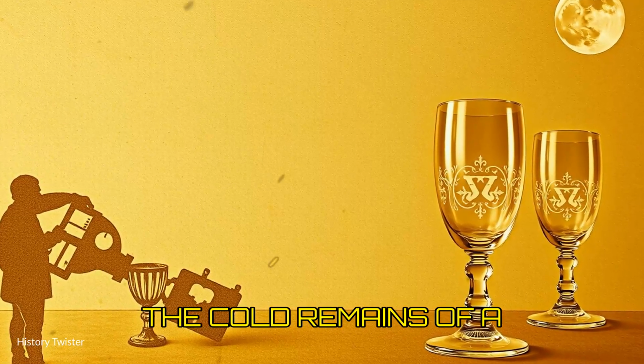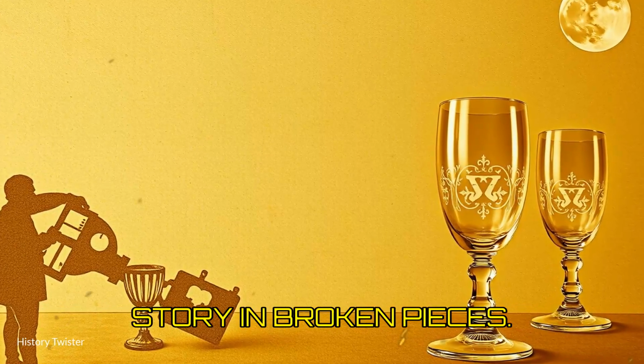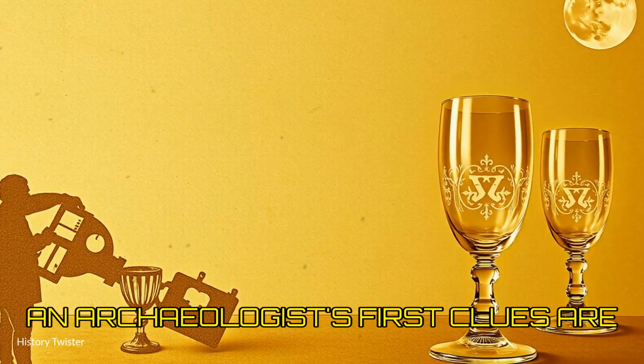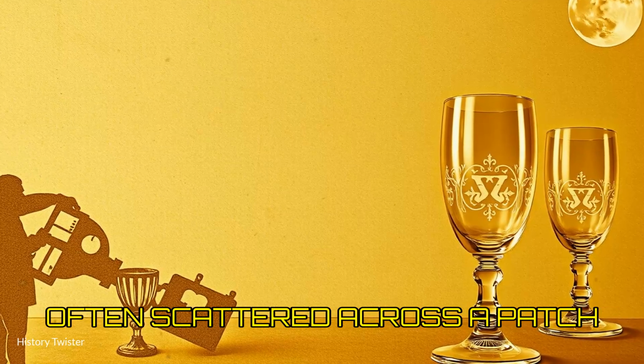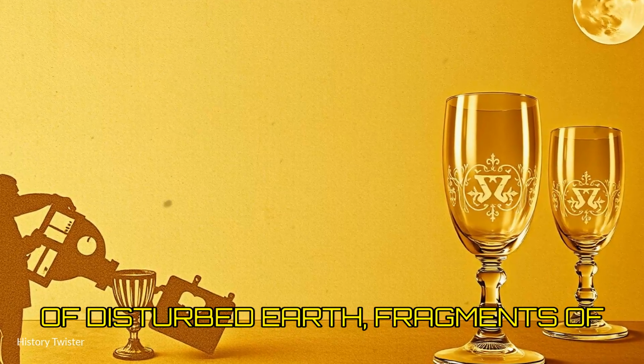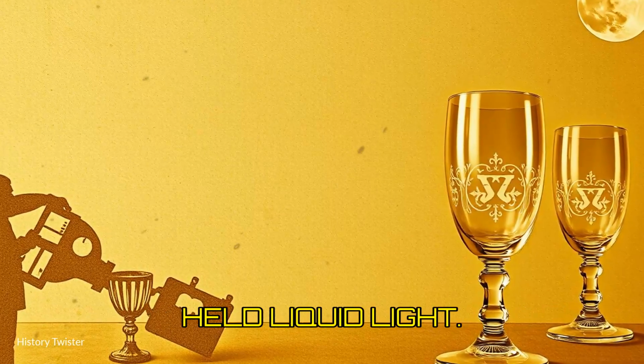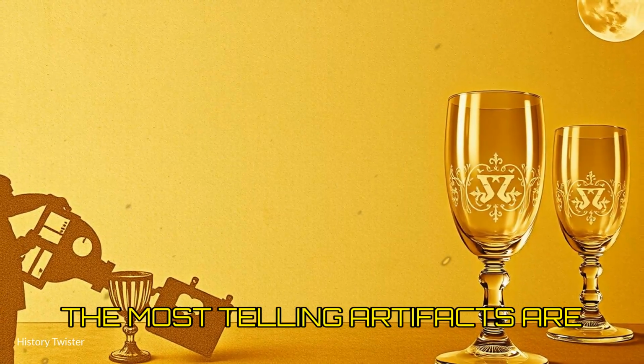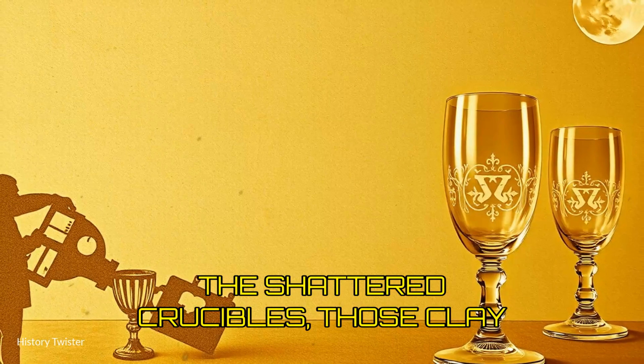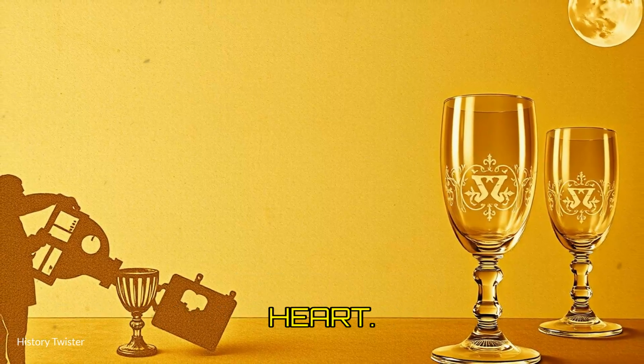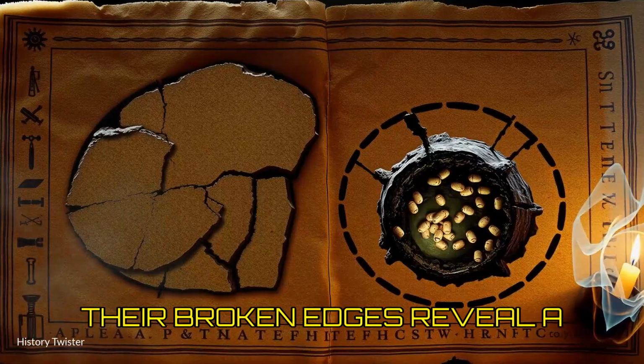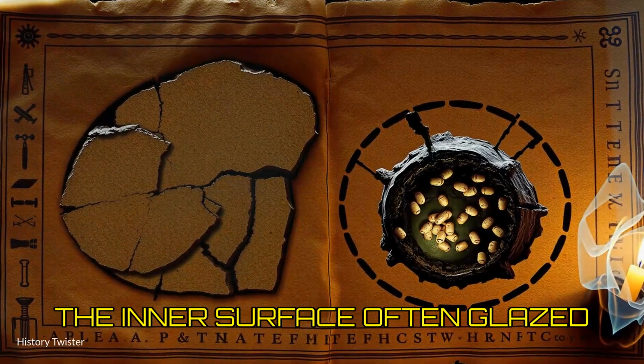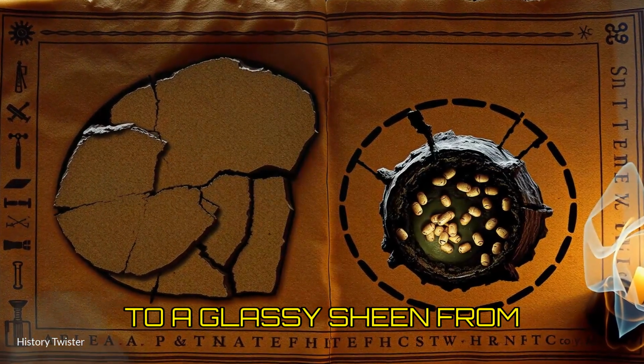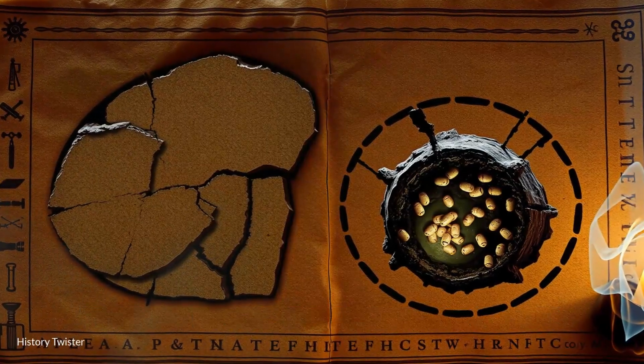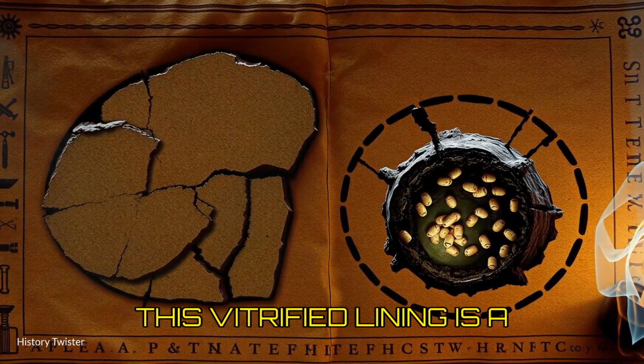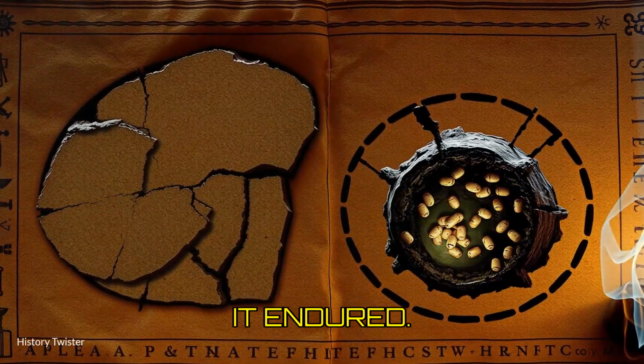The cold remains of a medieval glass workshop tell a story in broken pieces. An archaeologist's first clues are often scattered across a patch of disturbed earth, fragments of the very vessels that once held liquid light. The most telling artifacts are the shattered crucibles, those clay pots that braved the furnace's heart. Their broken edges reveal a cross-section of their history, with the inner surface often glazed to a glassy sheen from the intense, prolonged heat. This vitrified lining is a permanent record of the temperatures it endured.